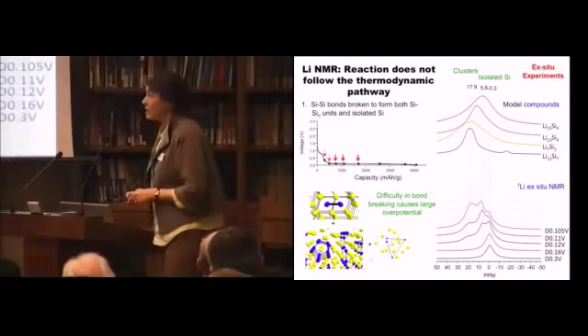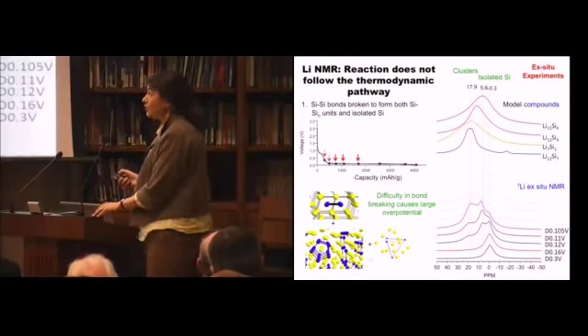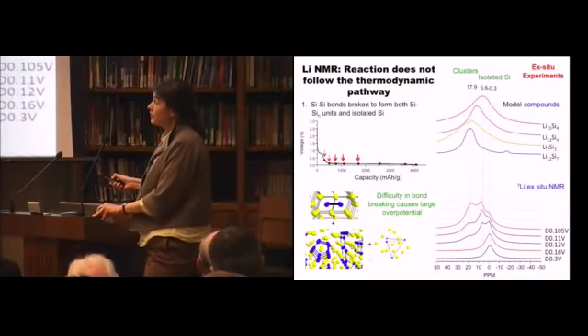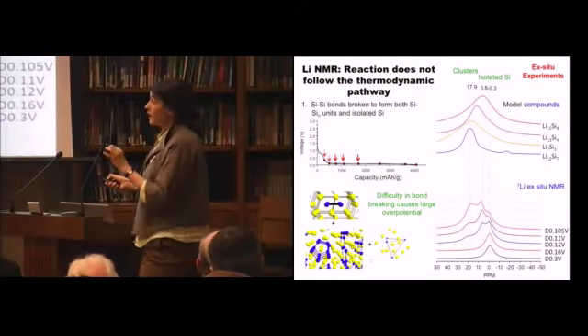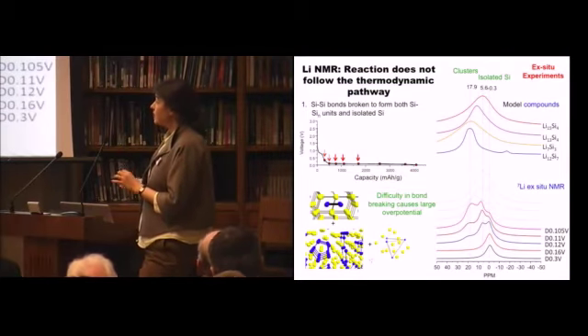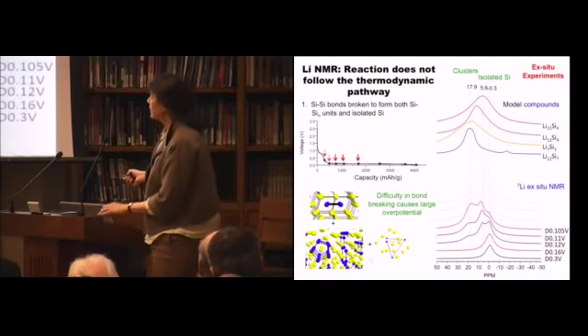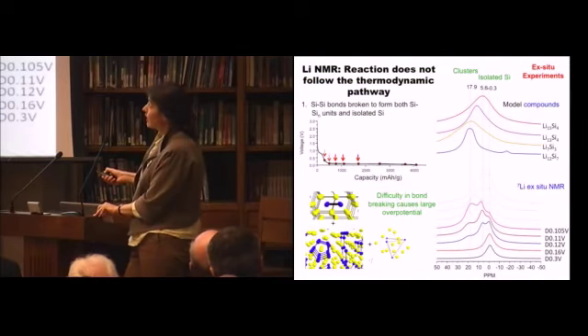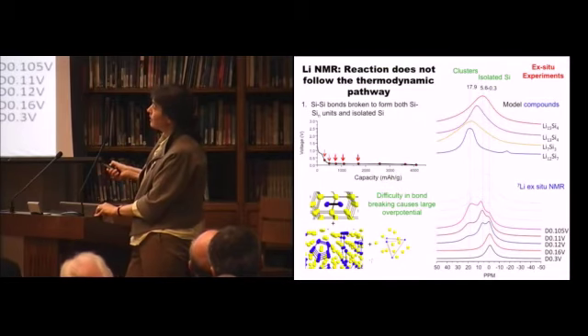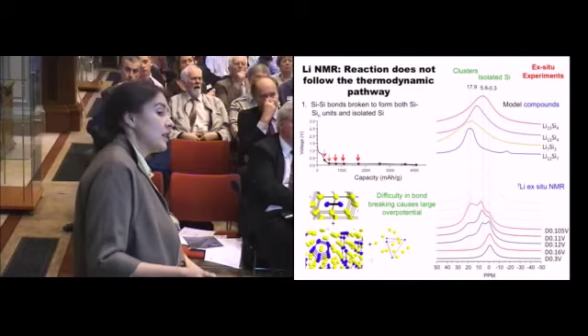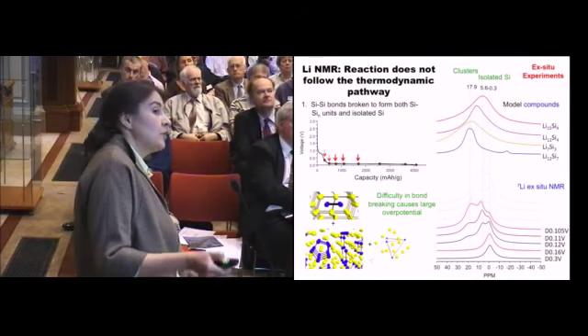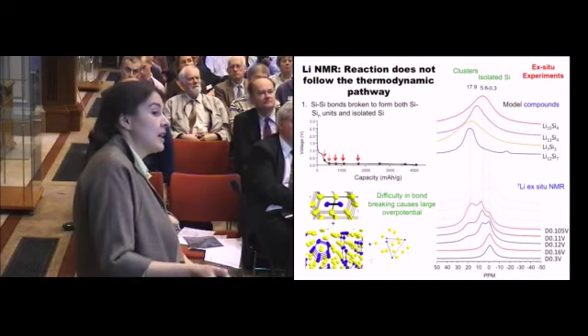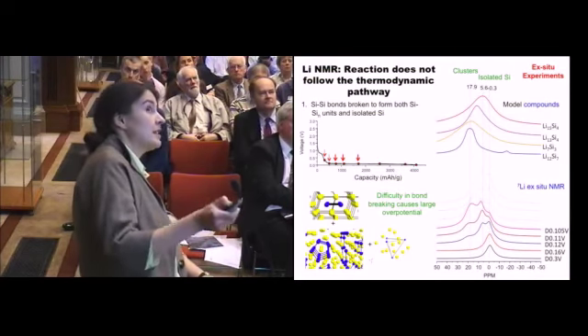So then I can make a battery, and I can see what sort of environments I have in my real battery. What I do is I make lots of little batteries, and I take them apart, and I run spectra on each of these batteries. The first two batteries are actually the reaction of lithium with the carbon in the material that I've added. And then the next ones are all lithium reacting with silicon. What's quite interesting is that as soon as you react with silicon, you see the peak that comes from the clusters, and you see the peak that comes from the isolated silicon.